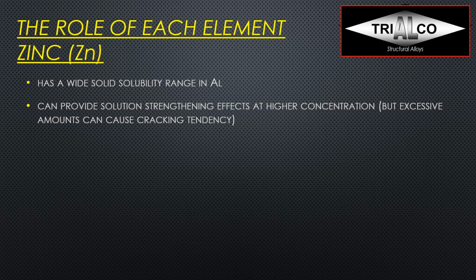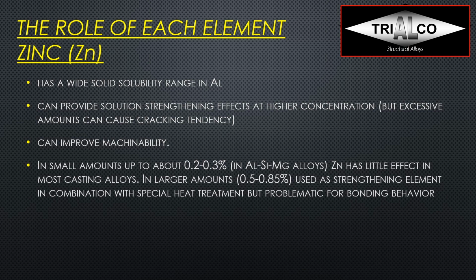So if I'm already high in silicon and in copper, so I have a very strong alloy, and now I'm adding 3% zinc, I might actually just crack the casting right before it comes out of the die. Zinc can improve machinability, and in small amounts, up to 0.2 to 0.3% in the aluminum silicon magnesium alloys, zinc has very little effect in most alloys. But if you go a little higher, and we see some alloys with 0.5 to 0.85%, it is used as strengthening alloys in combination with special heat treatments.